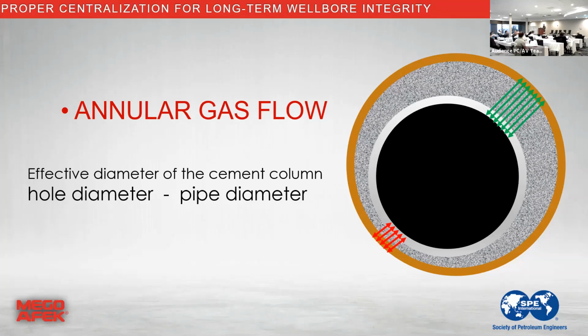But what if it's eccentric, like in this case? Larger diameter minus smaller diameter is still the same number no matter what. But on the lower side or the thinner side of your annulus, your gas flow potential is higher, period. You normally don't average out your diameter distances, and the assumption in a linear equation is larger diameter minus smaller diameter.